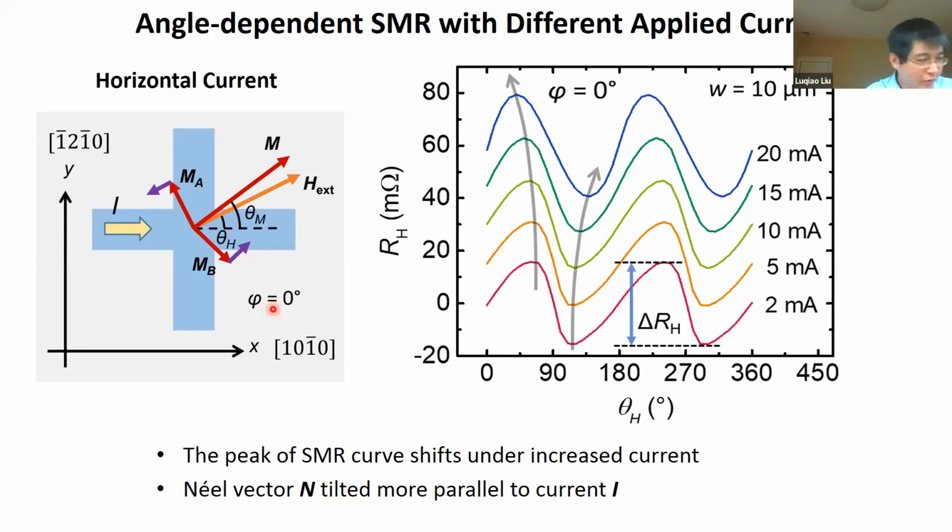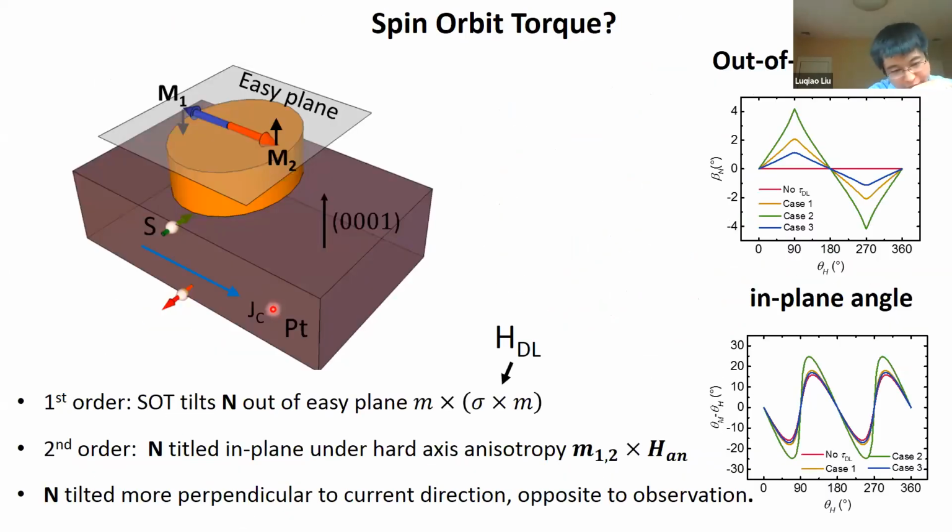That's a good question. Thank you for pointing this out. So yes, basically the spin-orbit torque will be more efficient if the injected spin is perpendicular to the easy plane. That requires you to grow the film in a different orientation. In principle, that's doable, but there could be some technical difficulties. The reason is when you grow it along some axis other than the c-axis, other things can contribute. Yeah, of course. But an appealing point is there might be an enormous Hall effect that can let you directly measure the direction of the weak magnetization if you grow it.